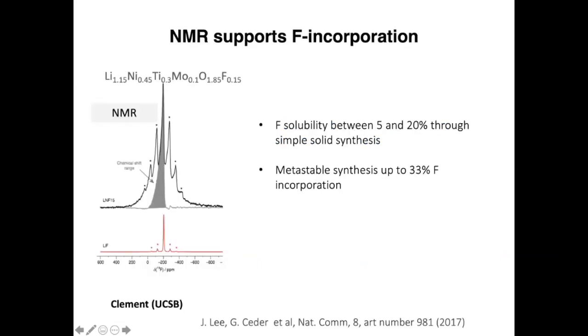This is work done by Raphael Clément at UC Santa Barbara, who's really been a tremendous asset in this research on DRX materials, because it's very hard to see fluorine in a material because you don't really see it in diffraction. So you really have to use NMR. And it shows very clearly that the fluorine is near paramagnetic metals and is therefore incorporated in the bulk. With simple solid state synthesis using simply lithium fluoride, nothing sophisticated, as a precursor, we can get between 5 and 20% of fluorine incorporated, depending on the chemistry and the lithium excess. If we go to metastable synthesis, mechanochemical ball milling, we can get up to 33% and maybe even higher.